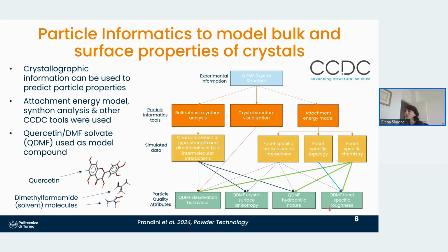And that information tells us a lot, again, on the facet-specific roughness, which can affect sticking probability and also flowability. We can get some information on the surface anisotropy and the relative hydrophilicity of the different facets, and also we can get some information on the desolvation behavior. So, for example, if we see that one facet is dominated by the solvate molecule, perhaps this is going to be the facet where it's easier for them to leave the structure. So if we maximize these facets, probably we might have a problem with stability.